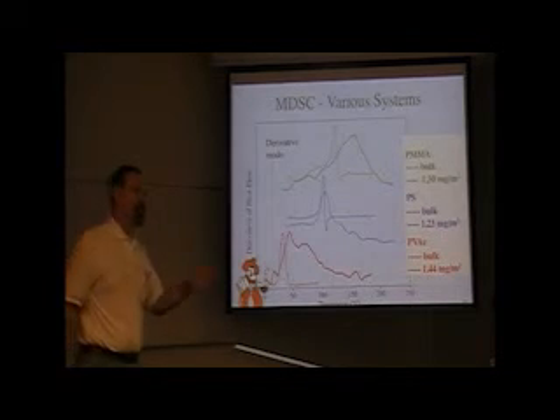So on the surface, the mobility changes, but not in an asymptotic way. It actually goes up and then comes down, which is really kind of weird, but it is. Okay, and in fact, in bulk, the mobility is higher, but it kind of goes like that. On the surface, it goes down to a minimum and then goes back up. And we can quantify all this, but that's the basic principle. And I should point out, I did it about 3 or 4 times. So you can also see this stuff with calorimetry. Now, I usually give talks to polymer chemists, and they don't understand much of this NMR stuff.